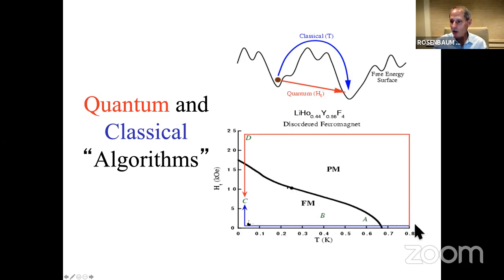In any case, what I want to do is compare different cooling protocols. So I'm going to call the blue one here classical in the sense that I'm going to cool down only with temperature, no extrinsic tunneling from the transverse field. And then only at the end, when I get to whatever low temperature I'm at, I'm going to raise the transverse field to a certain level here at point C. Alternatively, I can do the quantum annealing. That is, I can cool down, if you will, with a large transverse field on, so lots of tunneling. And then I'm going to come down and turn off the transverse field and come into the ferromagnetic state. And I'm going to come to the same point C. And my question will be, do I get to the same physical state? And how fast do I get there?